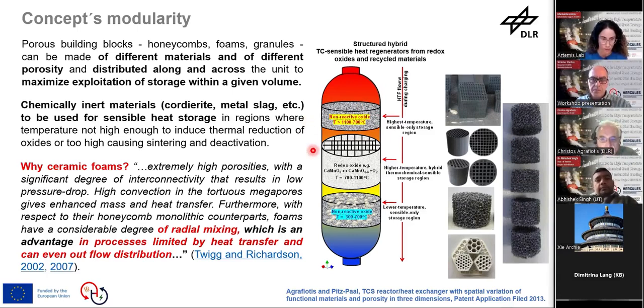One more word on why we select to use foams: simply because foams, in contrast to the honeycombs that are, let's say, unidirectional, allow for radial mixing. With this tortuous path that they have, the gas that goes in can flow not only along the main axis as you see it there, but also sideways along the radius of the cylinder, for instance, in the schematic. So this enhances heat transfer, evens out the flow distribution, and in general provides for better heat transfer from the gas to the solid during charging, and the reverse during discharging. And that's the rationale why we use such reticulated porous ceramic or ceramic foams.